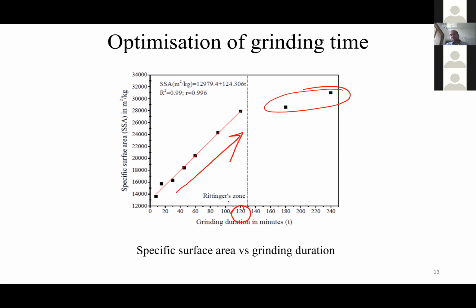Right. First we received the material, did the analysis for chemical composition, and checked whether it is amorphous silica or not. Then we moved to thermal treatment. In the thermal treatment, it is very evident that it is not giving amorphousness, rather it gives a crystalline phase, so we are not giving thermal treatment. Next, we moved on to grinding, in which we optimized the grinding time. Now the material is ready, so the first objective is getting completed.